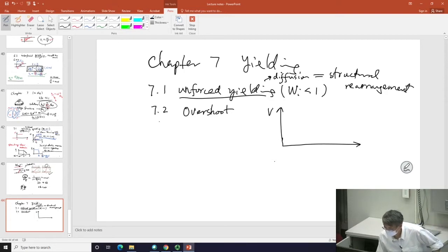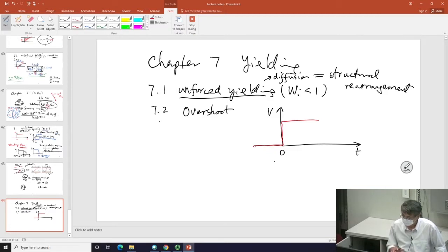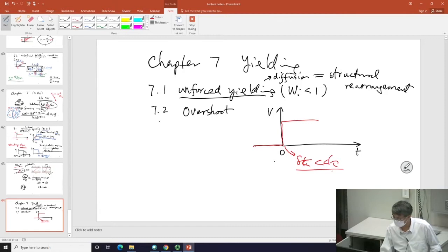And startup shear, of course, is something we have. I've said many times, basically you try to impose a certain velocity as quickly as possible. It's never instant, but as long as the time that it takes is very, very small compared to tau, we call that a startup. Remember, it's never instant. It always takes finite time, and it's all a matter of your instrument's time resolution versus your material's tau. So for water, you probably can never claim you have startup, because the tau is smaller than the instrument can apply to. So that's the concept.